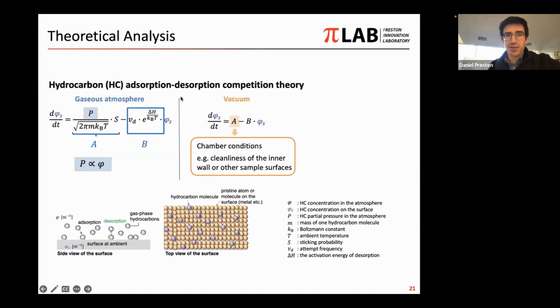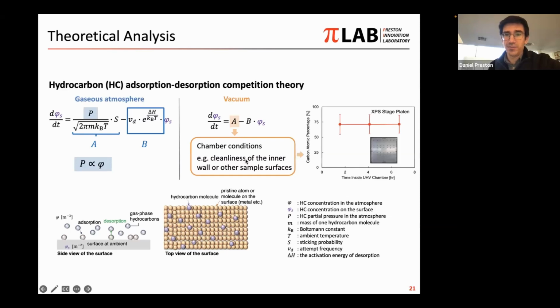In the vacuum environment, we could not use these exact same quantities, but we could still say that it's a competition between some adsorption, which might be related to the chamber conditions. For example, just looking at the stage itself, there's a lot of carbon present since the stage is coming in and out of the chamber many times during use. And then also some desorption that's related to the surface concentration of hydrocarbons.